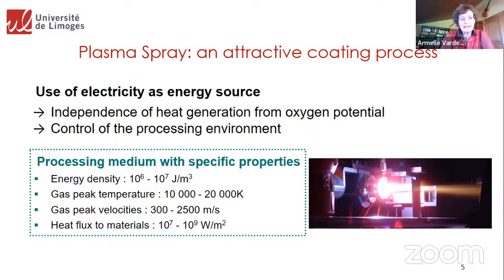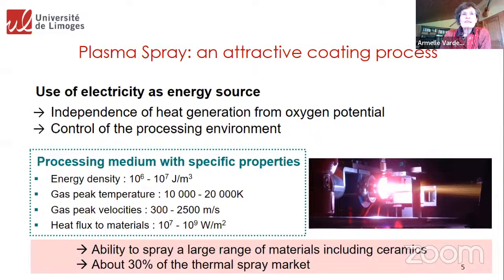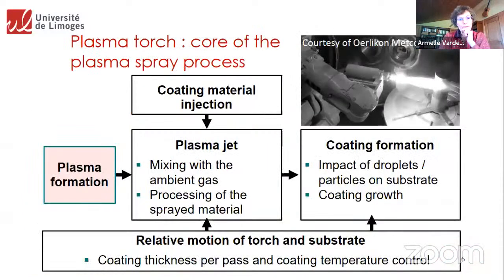Also, as you know, plasma is characterized by a very high energy density and very high temperature. We can go up to 20,000 Kelvin and even more now with the new plasma torches. We can reach very high velocity for the gas, up to 2,500 meters per second at the exit of the torch. And so this gas is able to bring very high heat flux to materials. With plasma, we can spray a large range of materials, but it's very well adapted to ceramics, and it's one of the reasons why we are using this in my institute dedicated to ceramics. Now, if we look at the thermal spray market, plasma spray is about one third. This was reminded by Professor Singh yesterday, and so it's an important process.